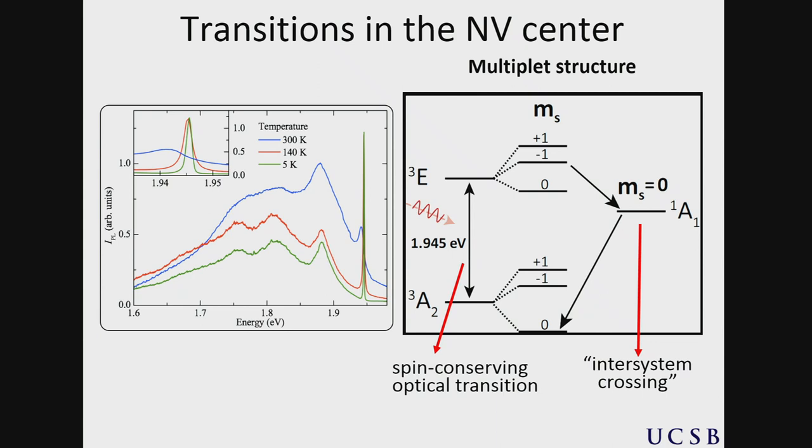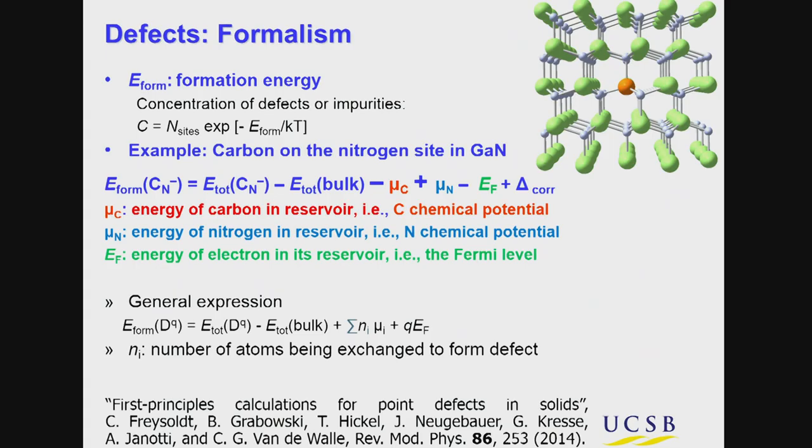So, I'm using this as an illustration to show that both non-radiative and radiative transitions need to be thoroughly understood. On the radiative side, here is a luminescence spectrum measured for the NV center. This 1.945 eV actually corresponds to the so-called zero phonon line, which I will tell you a little bit more about soon. But, as you can see, there is actually a very wide sideband which is caused by vibronic coupling to phonons which you need to thoroughly understand to really understand the properties of this system. So, that's what we set ourselves as a goal to study these line shapes and also to understand non-radiative recombination.